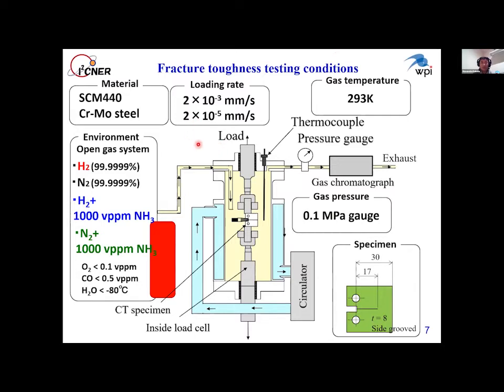We carried out a fracture toughness test. With these conditions, the material was SCM440 chromoly steel, and the environment was hydrogen, nitrogen, hydrogen plus ammonia, and nitrogen plus ammonia. The loading rate is one of the important variables for the hydrogen embrittlement experiment, so we used two loading rates, 2 times 10 to the minus third and 10 to the minus fifth millimeter per second. The temperature was 293 Kelvin, and the gas pressure at which the fracture toughness test was carried out was 0.1 megapascal in gauge pressure.